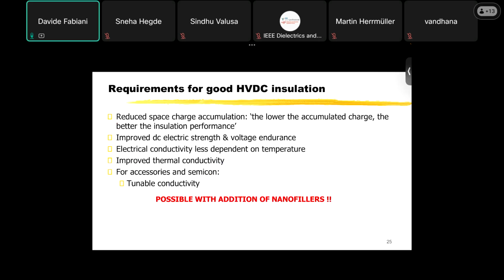So which are the requirements for good HVDC insulation? I've spoken a lot about space charge accumulation that should be reduced. The rule of thumb is the lower the accumulated charge, the better the insulation performance. But also what we want to get is improved DC electric strength and voltage endurance, or an electrical conductivity that is less dependent on temperature.